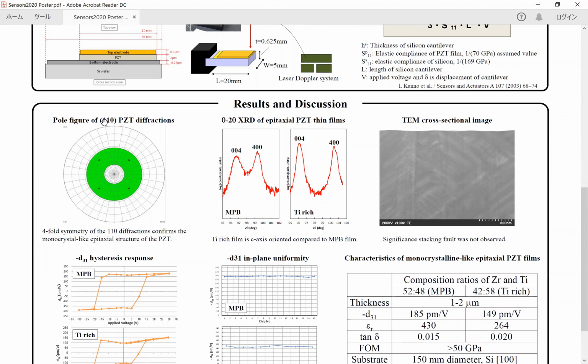This is the typical 110 pole figure for a 2-micron thick PZT film. The four-fold symmetry of the 110 diffraction shown in this figure confirms the monocrystal-like epitaxial structure of the PZT. The PZT is 001 oriented normal to the substrate surface and oriented in plane with a cube-on-cube structure relative to the silicon substrate. These figures show typical XRD patterns of MPB and titanium-rich films.